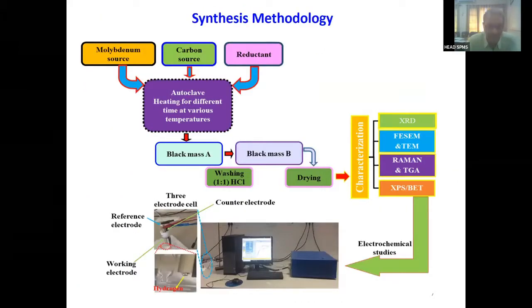Now, this is a very, very critical parameter. For the synthesis, carbides are normally synthesized at very high temperature. That means you have to take precursors, put the carbon inside and heat it to a very high temperature, something around 1400 degrees centigrade, for a longer duration. In this process, carbon diffuses inside the substance and eliminates oxygen in the form of either carbon dioxide or carbon monoxide, and the material is transformed to carbide, like tungsten carbide, WC, or molybdenum carbide, Mo2C.